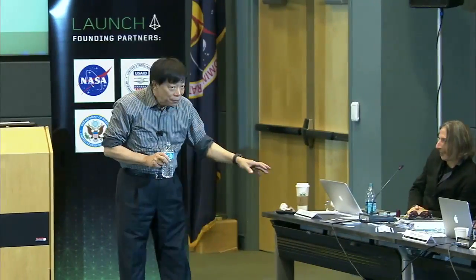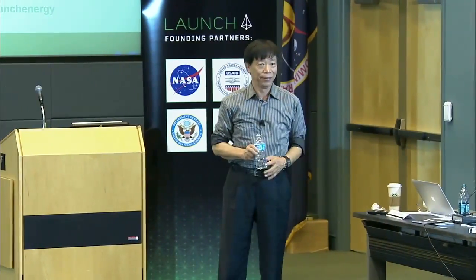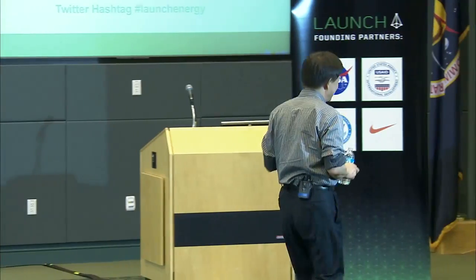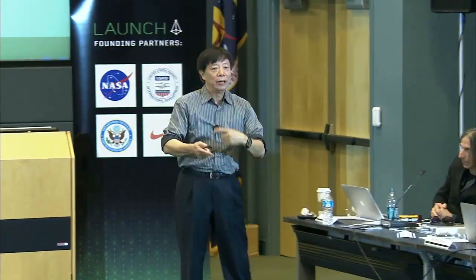Sponge. And this is 15 nanometer, okay, 15 nanometer. So we suck in a liquid. Using this, we call it nanocasting. Nanocasting is a cast. You cast conducting carbon precursors into the pore. And yin and yang, you know the yin and yang, right? Okay, so that is the way it is. Now the white becomes sucked in, becomes clear. It's in. And you can imagine, the pore becomes solid, solid becomes pore.